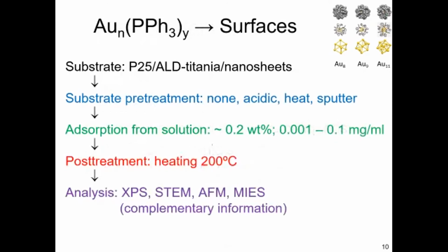We use a different substrate. We use a titania nanosheet, titania P25, which is anatase titania nanoparticles, and we sometimes do a pre-treatment to have this cluster attached to the surface, because it is not easy to immobilize. And we do a post-treatment.